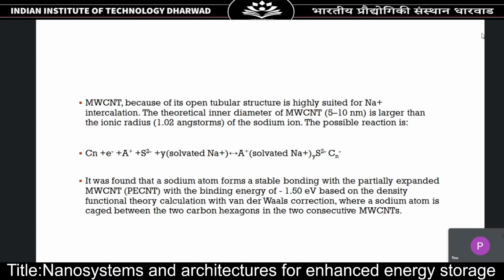So this is a reaction which has been proposed. You have the carbon coming from the nanotube, you have the sulfur which is used as an enhancer, and then we have the solvated sodium ion that forms a solvated complex during the sodiation. Sodiation means intercalation. And the solvated complex will dissociate during the desodiation or the deintercalation.